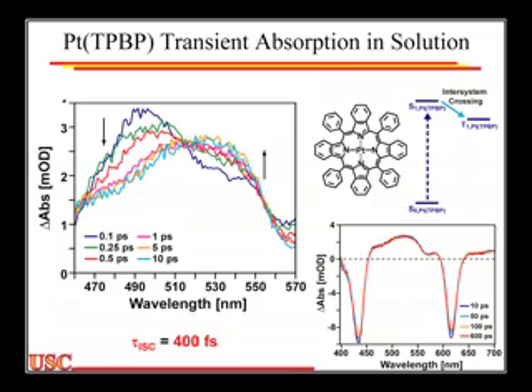If we wait longer, we go out 600 picoseconds, nothing's going on. That's because there is nothing to go on. This compound has a 50 microsecond lifetime. So once I get into the triplet, I'm there for 50 microseconds. And keep in mind, this is ultra-fast spectroscopy. So for them, a graduate lifetime in terms of scaling is a nanosecond. They can't go beyond a nanosecond. That's when their time constants run out, and their system won't go beyond that. So we're pretty far out. This is 3/4 of the way to as far as they can go.